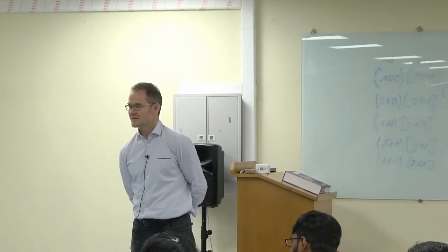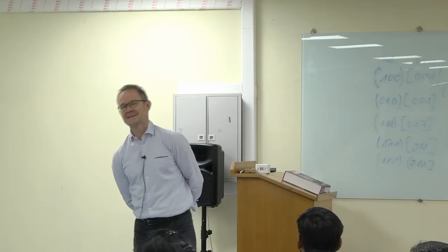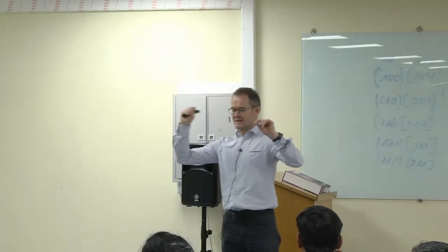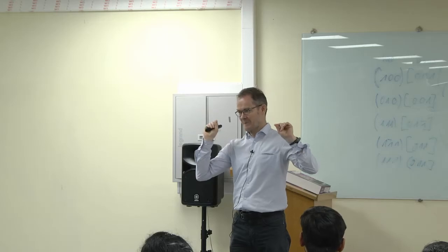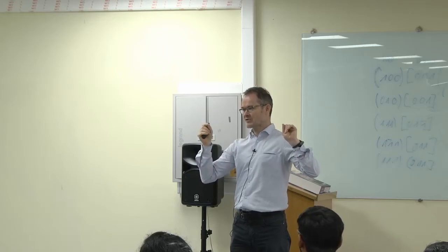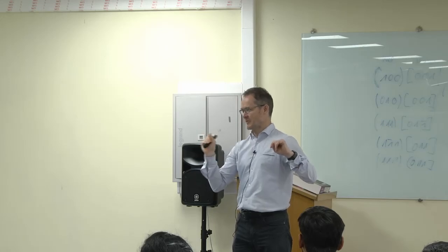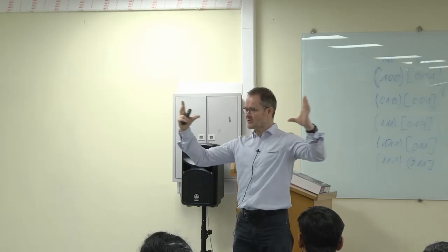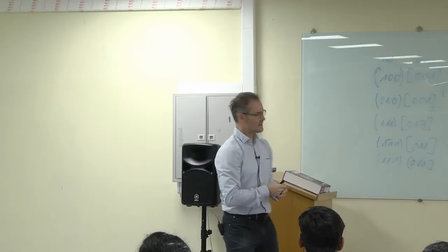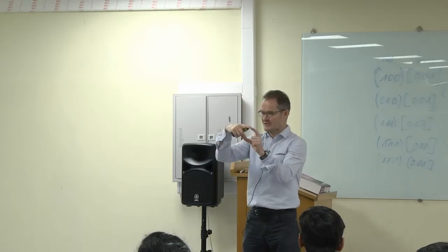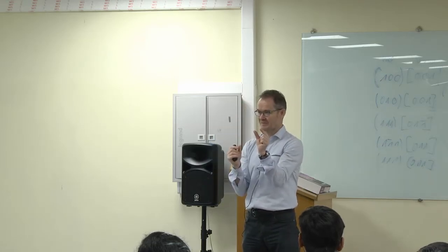Is that just the distance in Euler space between 2 points? You mean the Cartesian distance? Yes. No. In Rodriguez space, it is about the Cartesian distance, also not perfectly, but almost. But in Euler space, as the Euler space is compressed, the Cartesian distance is different from the orientation distance.